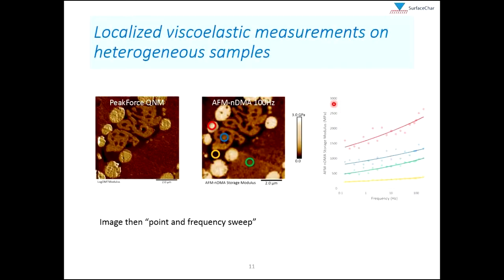Okay, thanks, Bede. So now I'm going to show some data on an expanded set of samples. Again, the general concept here from the workflow that Bede just described is the ability to make localized viscoelastic measurements for heterogeneous samples. So first you would image with a conventional AFM technique like PeakForce QNM just to find an area of interest. Here we had a heterogeneous 4-component polymer blend. So we found a good area that had representative domains for each.